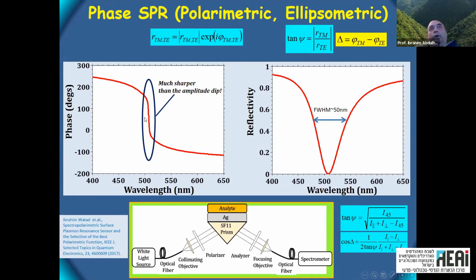And if you do it with a phase shift, similar to phase shift interferometry, like giving 3 phase shifts between the 2 polarizations, you can extract what's called psi and delta, the ellipsometric parameters, from 3 measurements. You can do it in parallel, then you get much better improvement. Besides, we found that this phase curve is less sensitive to the variations in the thickness of the metal itself. So you have less tolerance requirements on the metal thickness.